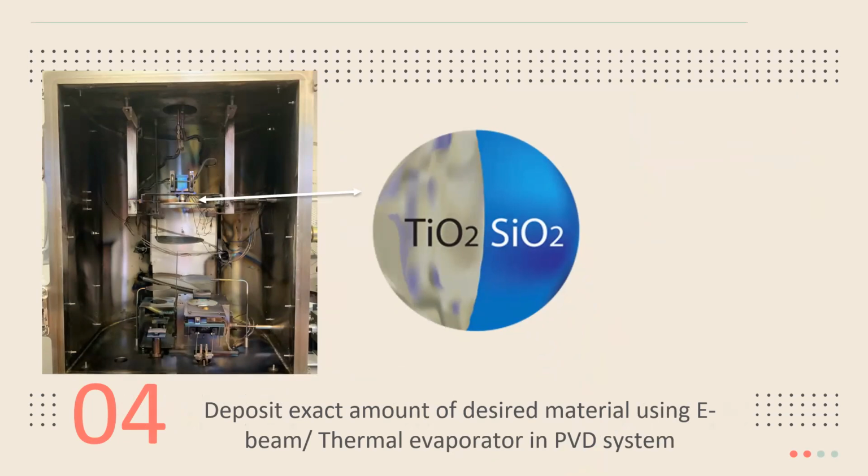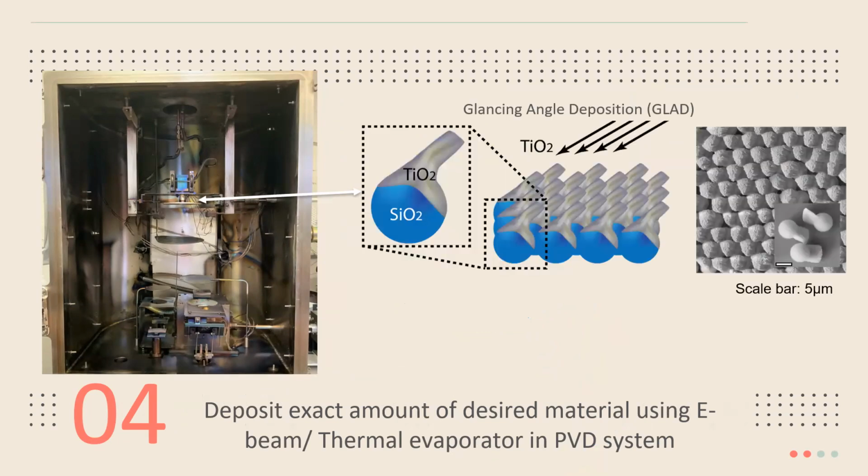And the cool thing about our chamber is by just depositing more, we could create different shapes and structures. So here's just a Janus sphere, sort of a thin film deposition. But when I deposit more and with the use of my glancing angle, so by me changing the angle that the substrate sample is being held at, I'm creating this shadowing effect to create these tail-like structures on my microswimmers.